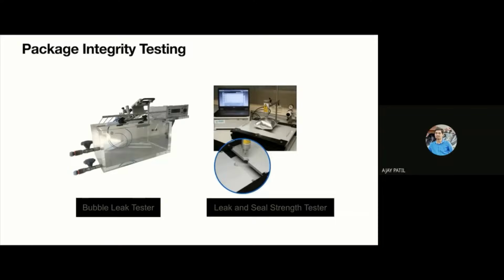To give you an example, a bubble leak tester can very quickly tell you if there are any micro leaks inside a package. This can be very important because small micro leaks can allow micro channeling, which could permit spores of fungi or various pathogens to get into the package and contaminate the package. And sometimes consumers don't always check the package before they consume it, and this can lead to hazardous consequences.